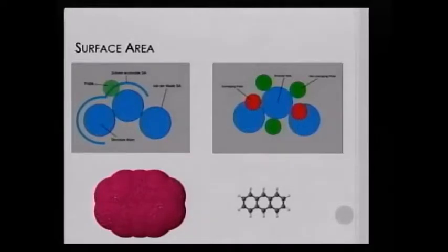Once again, I employ a method that's based on Monte Carlo, but in this case, it's a little bit more sophisticated. So for each atom in your system, what you do is you create a number of probes that are distributed evenly along a sphere of radius that you define, for example, and start to add probes along this sphere. And you can see here some probes will be accepted as they don't overlap other atoms, and some will be rejected. And when you consider this, and you do this for all the atoms in your system, you can end up with something that looks like this.